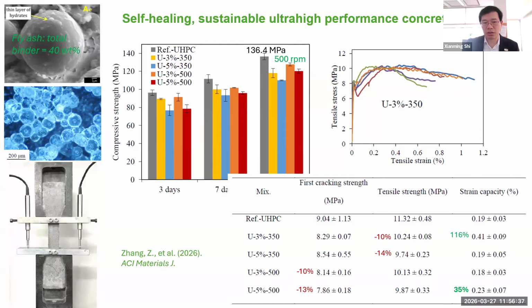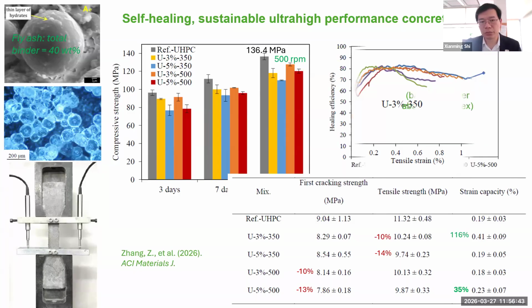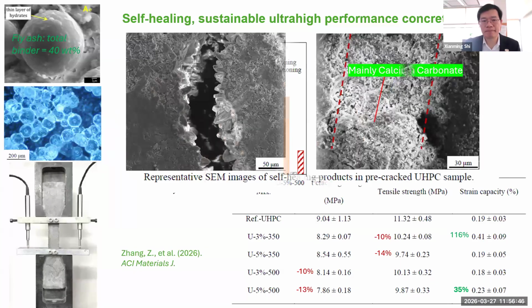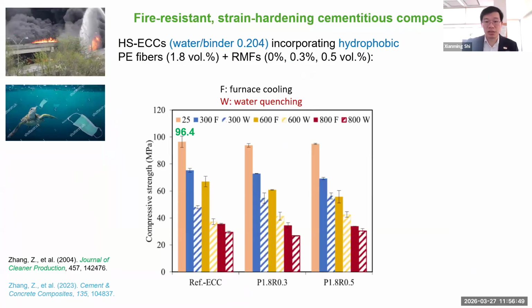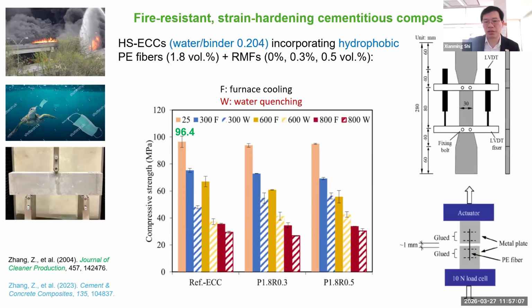In that case, the healants are no longer these chemicals. They are a mixture of two different types of bacteria. Now, yet another one is, again, ECC or strain hardening cementitious composites. We demonstrate that we can use very cheap recycled masks or recycled clothes to endow the ECC with much better fire resistance. Basically, without it, the ECC would have this explosive spalling, but with it, they are basically sort of intact under fire attack.